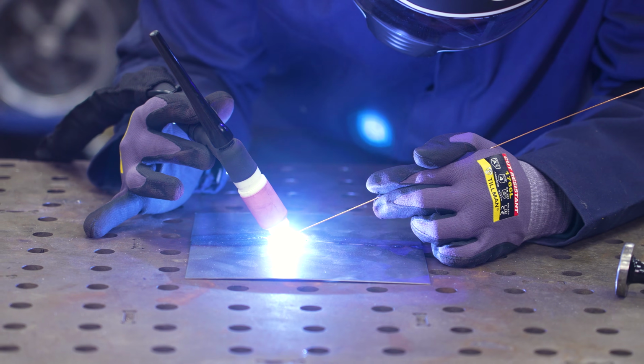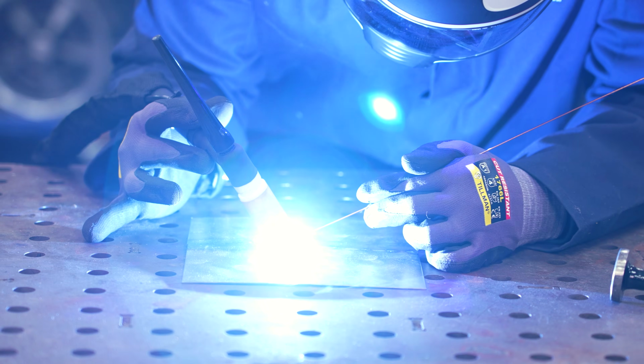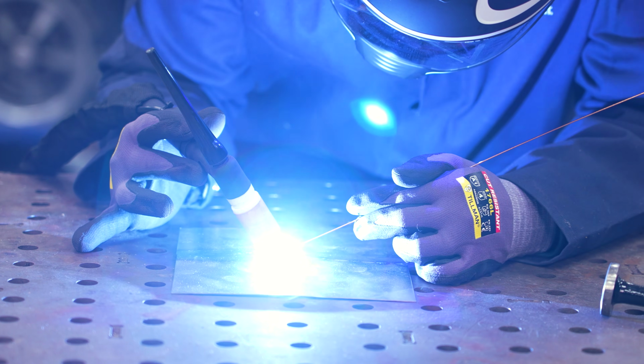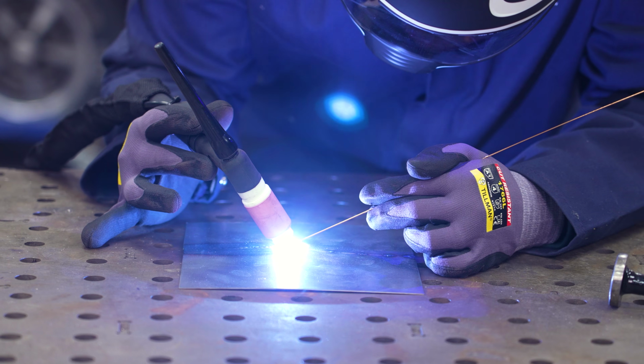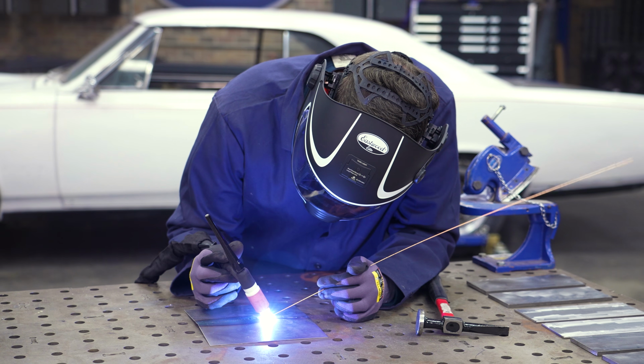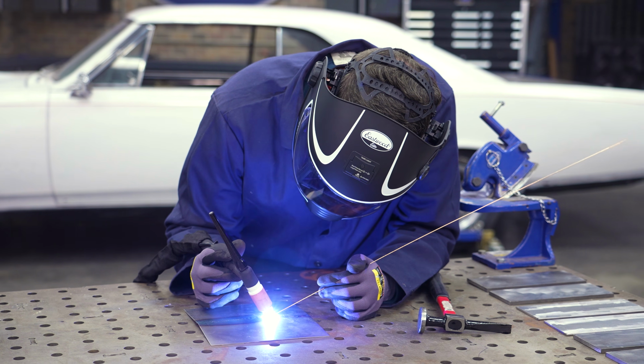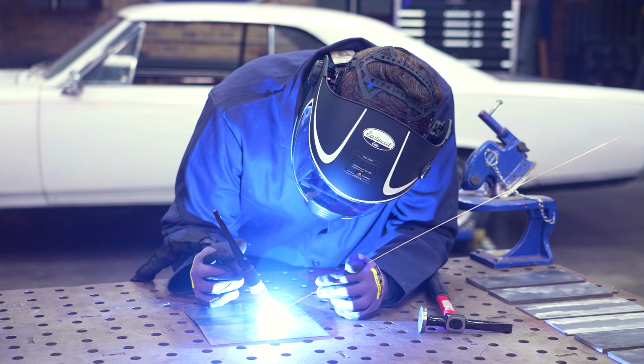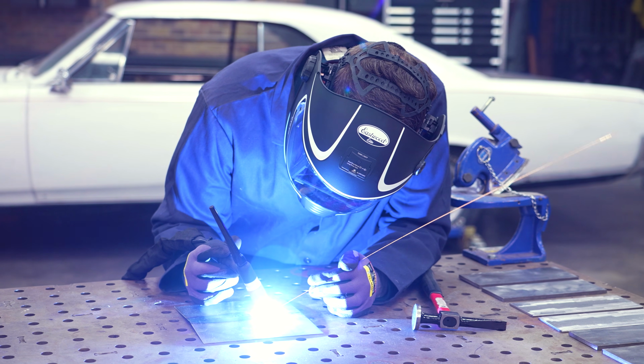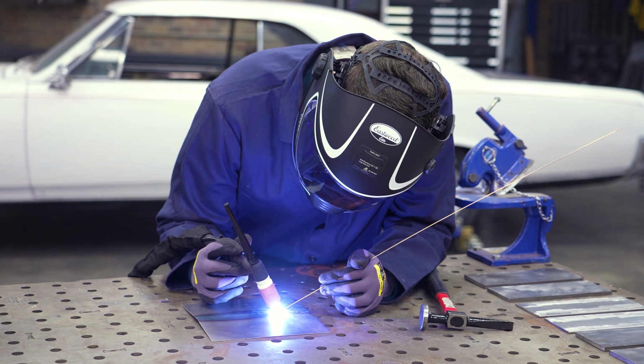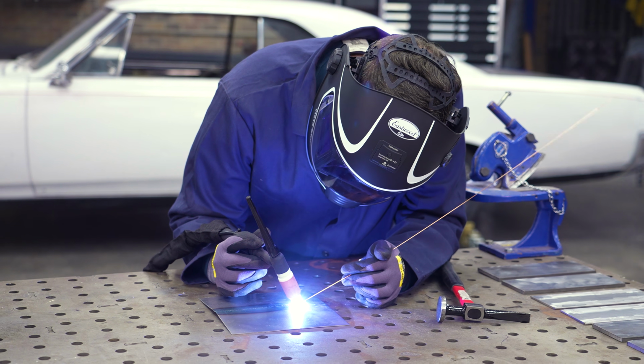Because when you're welding sheet metal, consistency is very important. If you keep doing the same thing, you're going to have a very consistent shrink afterwards from that weld to then planish. What's nice also about the slow pulse is I can really watch my puddle and see when it's going to begin dropping through, which will give me a good indication of the penetration I have. And also, when I've gone a little too far, it might blow through.